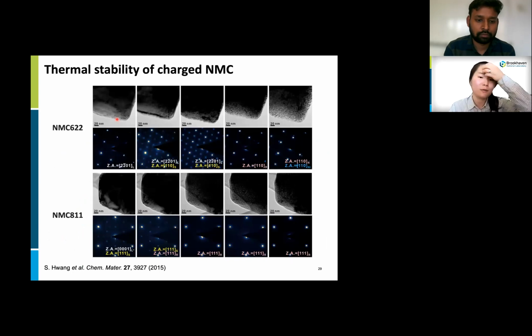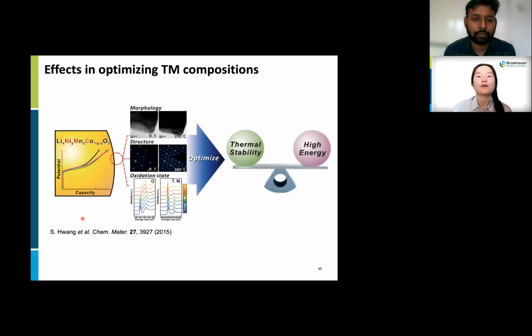This trend is also found in imaging and electron diffraction patterns. Porosity evolution and phase transformations were observed at much higher temperature in the case of NMC622 compared to NMC811. So from the systematic in situ heating experiments with different compositions of NMC materials, I could suggest that optimizing transition metal compositions can be an effective way to achieve thermal stability and high energy simultaneously.